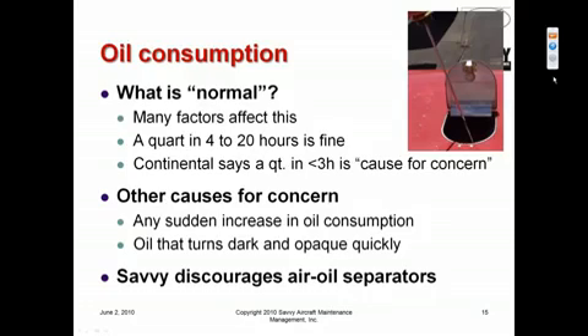In fact, I remember early when the Continental powered Piper Malibu was introduced, it exhibited almost zero oil consumption. Everybody was very, very happy until the engines got to about 500 hours and suddenly started wearing out cylinders, and it turned out that there wasn't enough oil getting to the upper portion of the cylinder barrel, and so there was very accelerated wear. Continental wound up reducing the tension on the oil control rings in order to get a little bit more oil on the cylinder walls. That caused oil consumption to go up somewhat, but drastically increased the longevity of the cylinders.